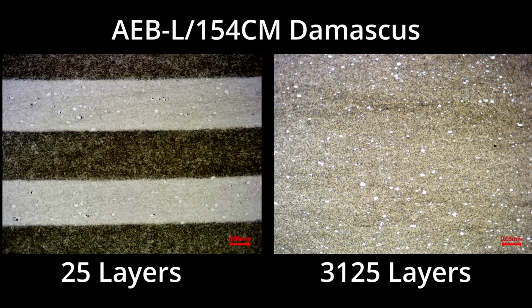How can I be so sure they cannot be eliminated? Well, we did a study, my father and I, with 154cm AEBL Damascus. AEBL is the same as 13C26. It has very fine carbides. 154cm is a conventional steel with higher carbon and chromium, and it has larger carbides in it when it's made conventionally. And what we did is we started with only 25 layers, but also forged it all the way out to over 3,000 layers, where the individual layer size is smaller than the carbide size in the 154cm. So this steel saw a ton of reduction to an effective amount of the steel only being a micron thick. But the large carbides are still present. We could not get rid of them.